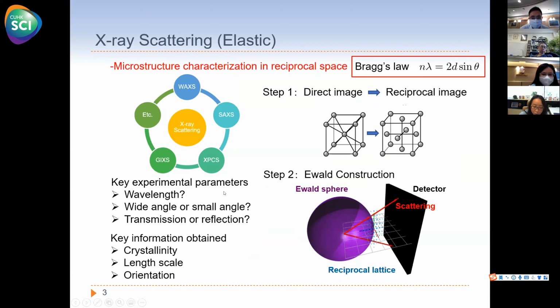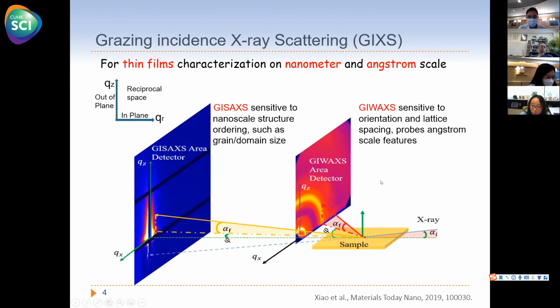How we choose the probing beam wavelength and how we perform the measurement, whether we collect wide angle or small angle scattering, whether we do transmission mode or reflection mode, will determine the key structural information that we can extract. For instance, crystallinity, the length scale, the orientation of the microstructures. The solar cells that we are doing research on are in thin film structure. Here, the symmetry of the structure breaks into out of plane and in plane directions.